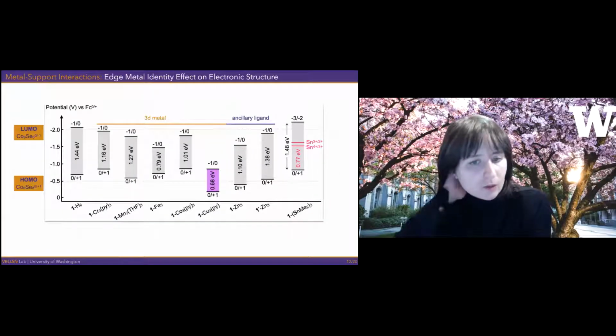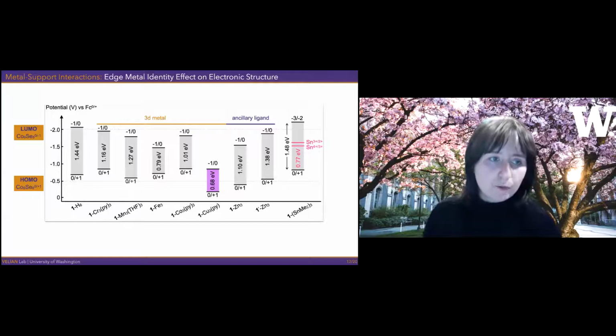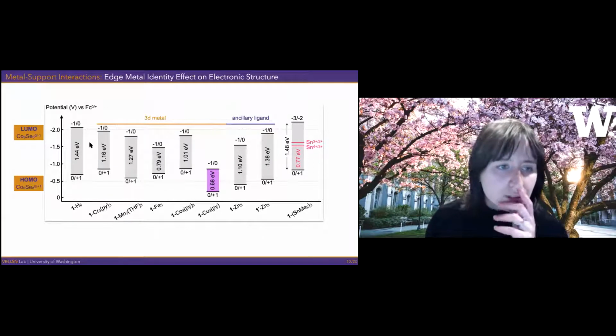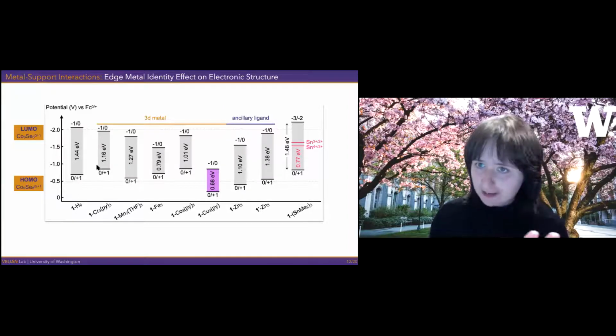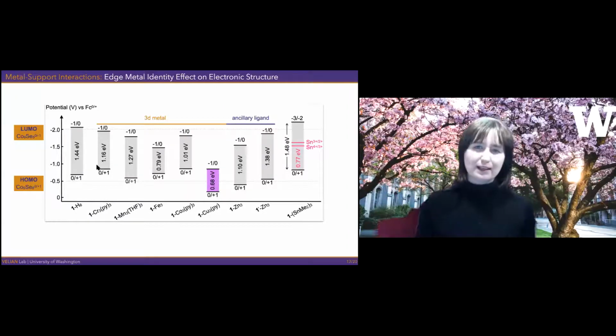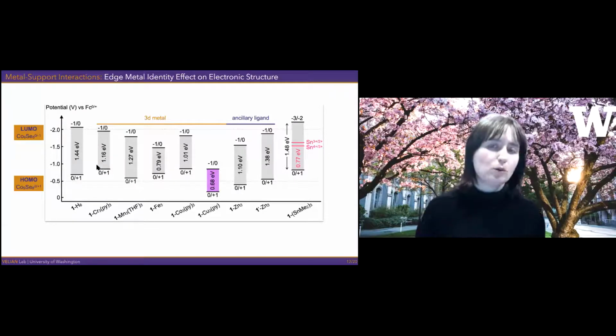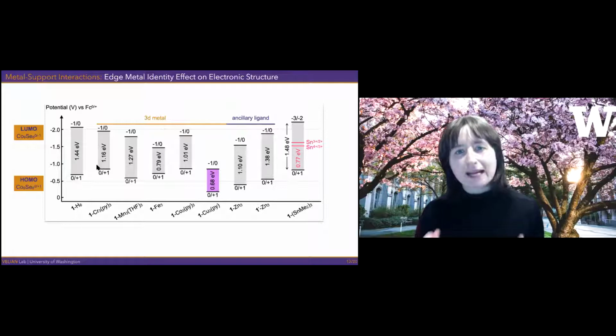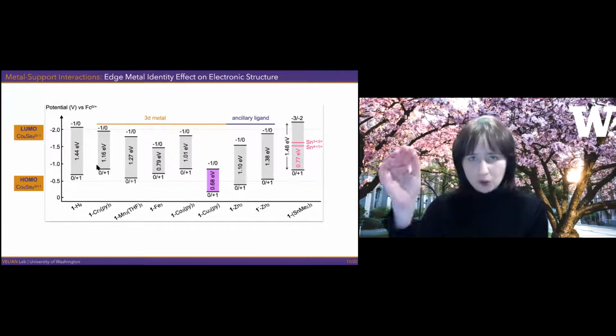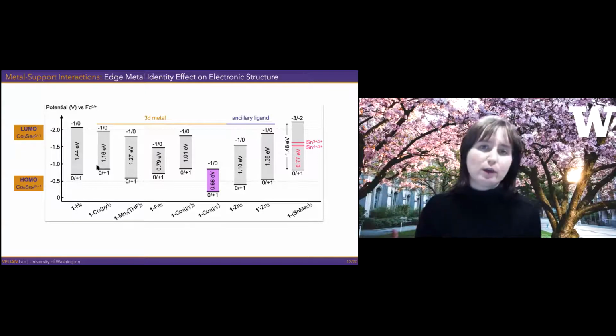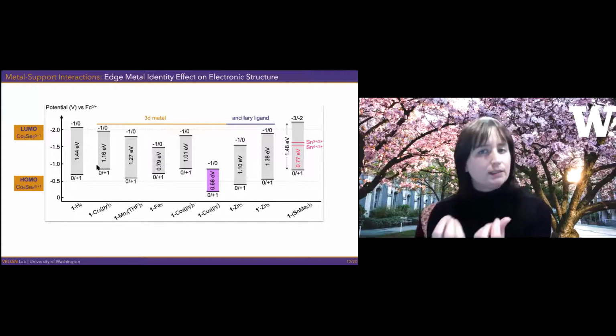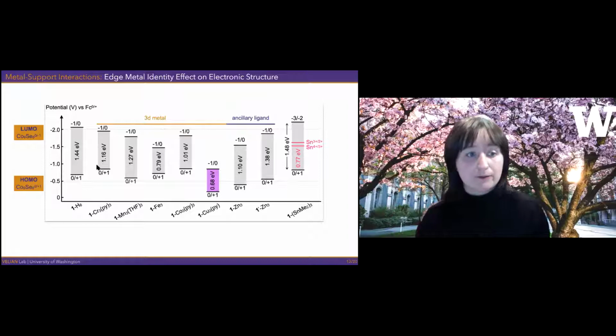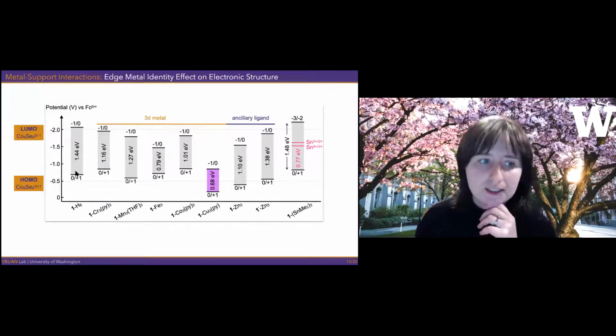And so we can do this kind of analysis, and we do it for all other derivatives. And so here's just a snapshot of how this HOMO-LUMO gap changes in the series. The reason why the HOMO-LUMO gap is important is because it really tells us about the reactivity of the cluster. If you have a really large HOMO-LUMO gap, then that's typically associated with very stable molecules, right? So sodium chloride has a very wide band gap. Whereas here we want to see something that is shrinking in its value from the naked cluster. So here's the naked cluster. It's 1.4 eV. That's fairly large.